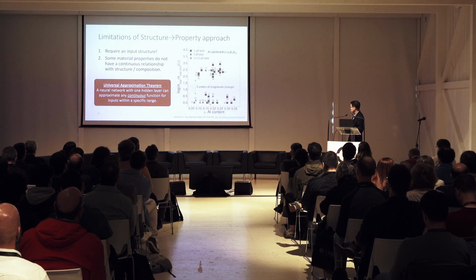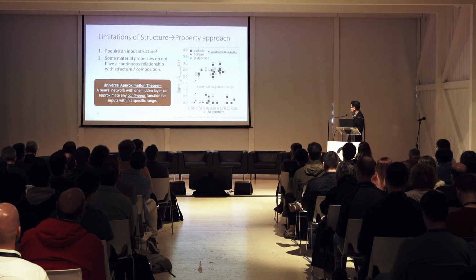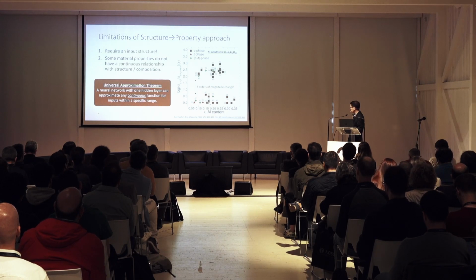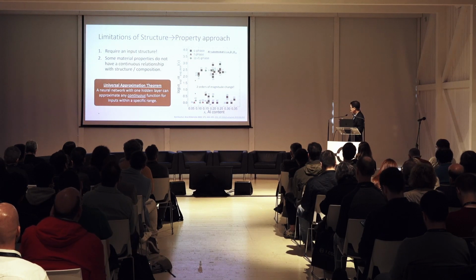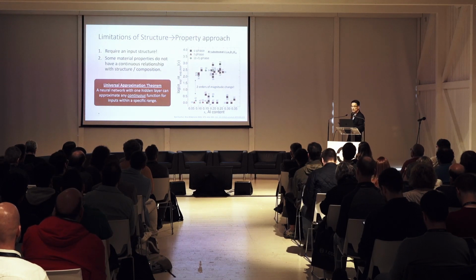Now people have studied this system extensively. They try to dope aluminum into this LLZO material and they measure its conductivity. And I want to point out that this y-axis is actually a log scale, okay? And what you notice is that just by changing the composition by very tiny amounts or the structure by a very small amount, you can already have a 2 orders of magnitude change in the ionic conductivity, right?